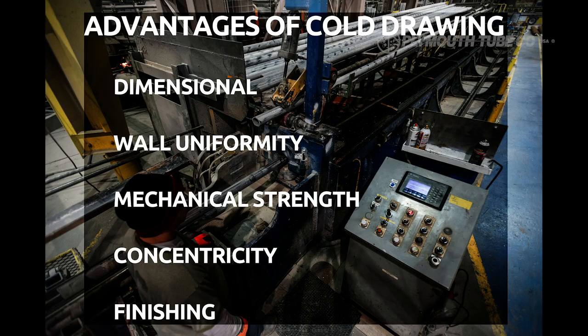Some advantages of cold drawing are dimensional, tight tolerances. The cold drawn process is capable of providing approximately half of the traditional roll-formed OD tolerance. These tolerances can be significantly tighter than seamless cold drawn tolerances, since the welded hollow is very concentric. When this process is performed, the weld can be very difficult to distinguish. The cold drawing operation provides an ironing effect on both the OD and ID surfaces. This smooths the surface, thus reducing the roughness commonly measured in RA. Typical surface finish of a cold drawn material is in the 20 to 30 micro-inch RA or better.